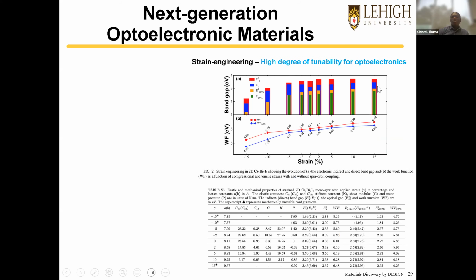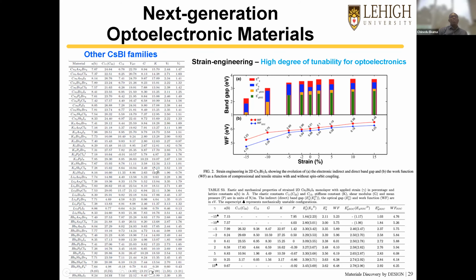We further also show that we can tune these materials using strain. So what I'm showing here is the strain. As we increase the strain, it responds, because it's very flexible. A strain above 10 for compression and 15 for tensile generally leads to mechanical instability in the system. We did also carry out some other high-throughput material screening of a related family, and we did share the whole CIF file and information of all these materials. We didn't really study these ones in detail, but we just tried to demonstrate which of them is mechanically stable and could be further screened for potential application.